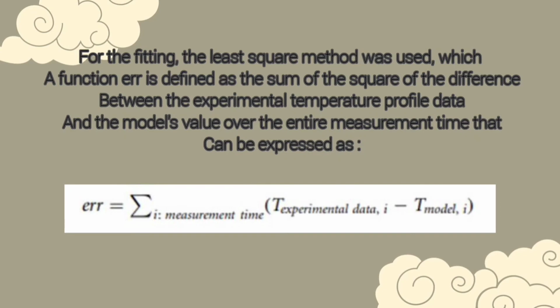The thermal conductivity of the 3D CNT network is contributed by the intrinsic thermal conductivity of the primary CNT, the intrinsic thermal conductivity of the secondary CNT, and the thermal conductivity of the air gap, which depends on the filling factor of the tubes. The growth of the secondary CNT decreases the air volume fraction and enhances the thermal conductivity of the 3D CNT network. The other reason for the enhancement is that the secondary CNT works as extra channels to transfer heat at the top surface downward through the CNTs.